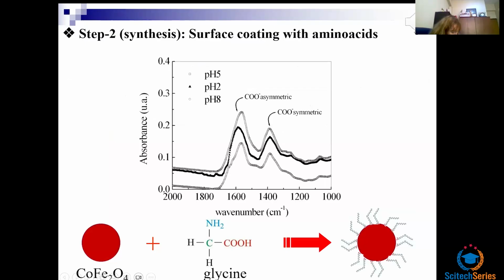This slide shows how the surface coating of the freshly precipitated cobalt ferrite nanoparticles can be performed. So we do the surface coating at different pH, and actually we can track the surface grafting of the coating using optical measurements. Actually, we look at the absorbance, and then we can find the highest absorption regarding the carboxylate group, looking at the asymmetric and symmetric vibrations of the carboxylate. So the highest intensity in absorbance indicates the best pH to perform the surface coating.